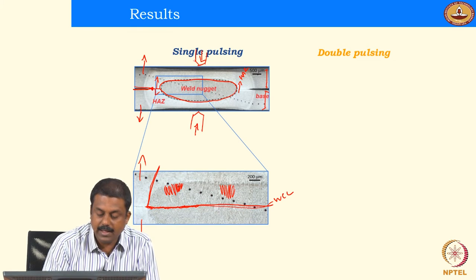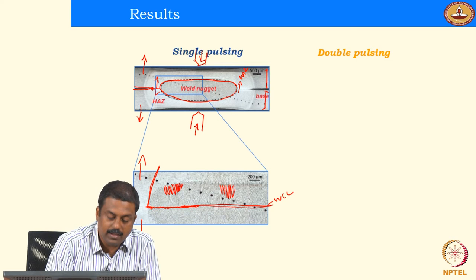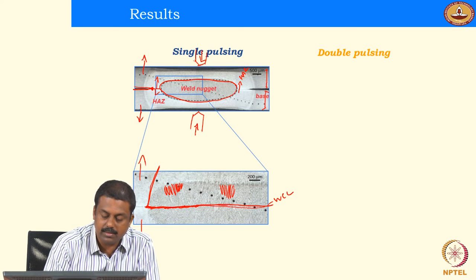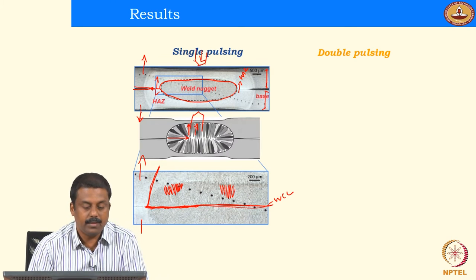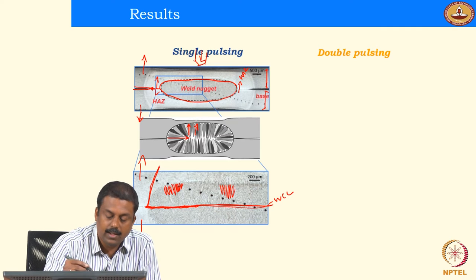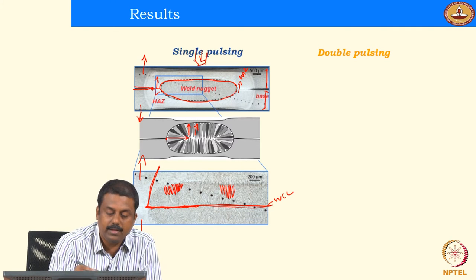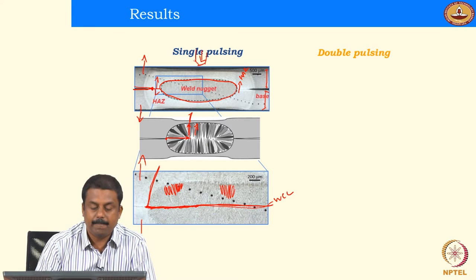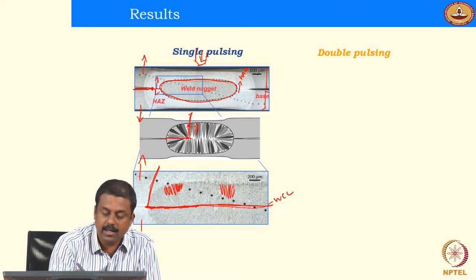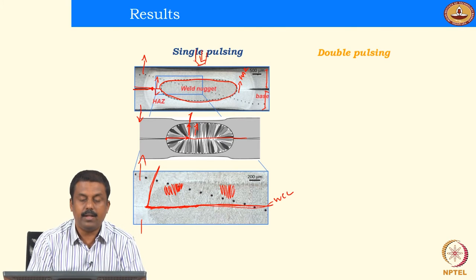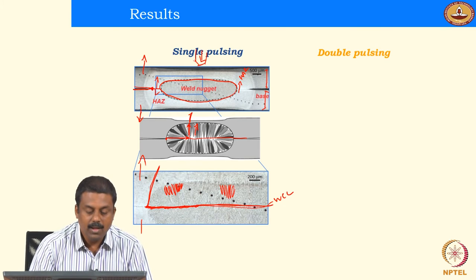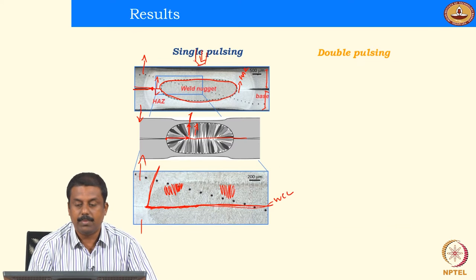But because of the segregation of alloying elements at the weld center line, if you have carbon and phosphorus segregation, you will have a crack propagating from the tip of the fusion boundary and going towards the weld center line. Say, for example, you expect a crack to nucleate at this region and propagate, and the moment it reaches a critical limit, because of very strong segregation, you will have a failure of the plug, whether it is partial. And if you have a high segregation, you will have a complete interface failure where we have a plug ratio of 0. Okay, so now what happens in double pulsing?